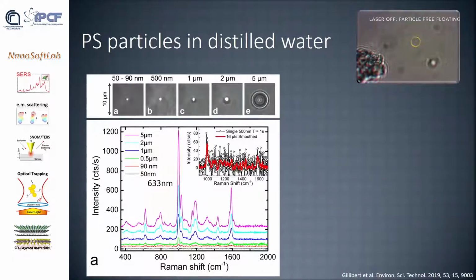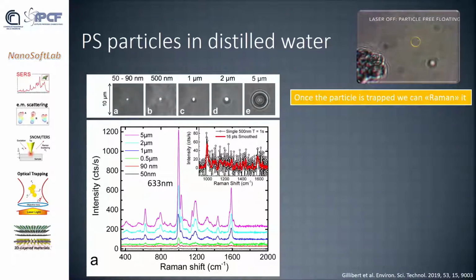Let's see some examples. Same move as before: the particle fluctuates, we trap it. Once trapped, we can keep it in the trap as long as we want, and we can get the Raman spectrum. Here we see the optical images, the top images of particles going up from 50, 90 nanometers, half a micron, 1 micron, 2 microns, and 5 microns.